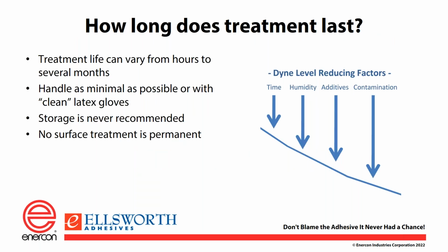The other question that gets asked all the time is how long does the treatment last? This could be, again, from hours, or actually seconds in the case of fluoropolymers, which don't treat very well, to several months. We do have some batch applications, not very many, where somebody treats a part and then puts it in a batch and prints on it or something later. That can happen if you only need a slight increase in surface energy, but it's not optimal. You're creating a highly active part, so we always recommend that you do whatever the next process step is, in this case bonding it, as soon as possible after the treatment. It leaves the least room for mistakes and things to happen.